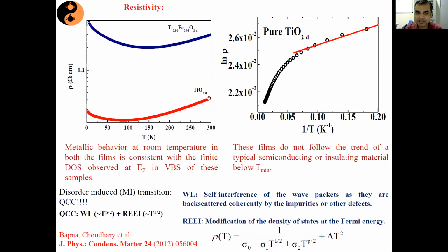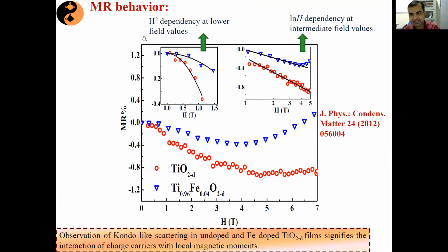So you can see here that this is positive, whereas in this particular region, when it becomes semiconducting again below say 100 Kelvin, it is negative in nature. Okay. Now, what about the spin polarized charge carrier? If you look at its spin polarized charge carrier, what does that mean? That means if I apply the magnetic field, then the resistance of the material should change, right? How do I confirm that?